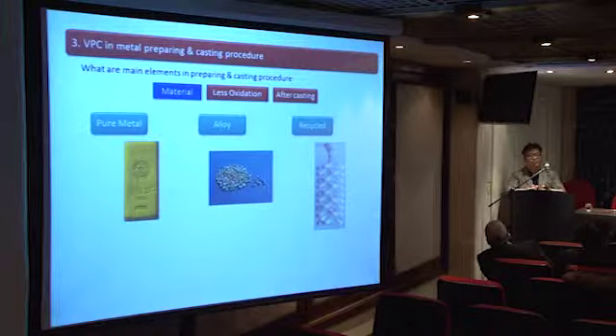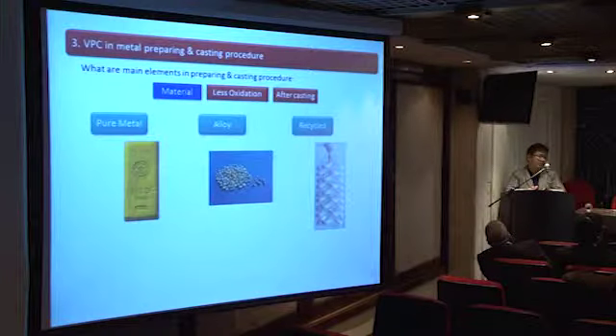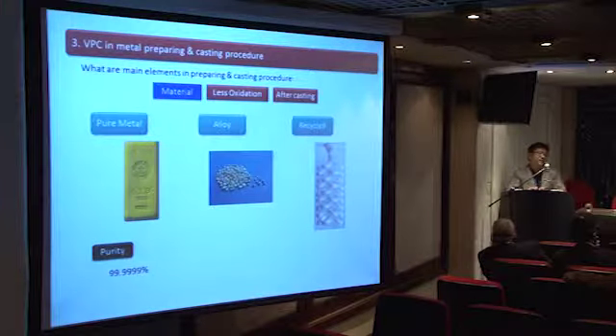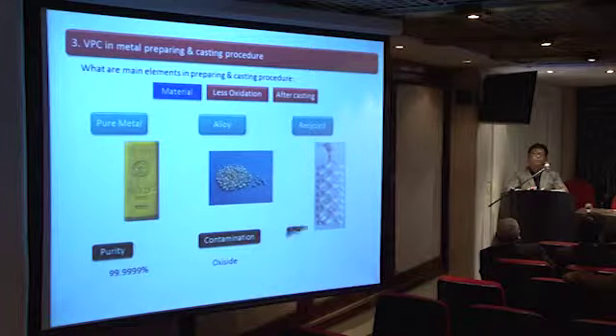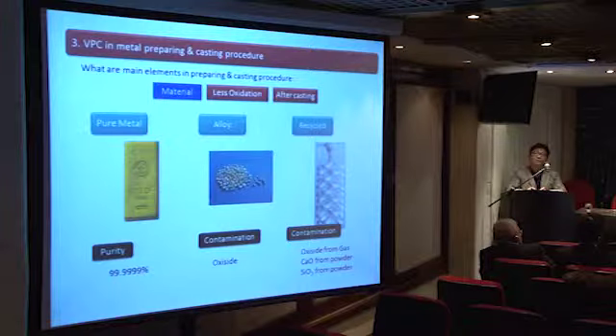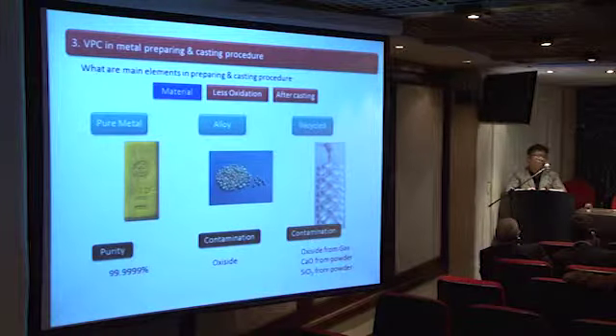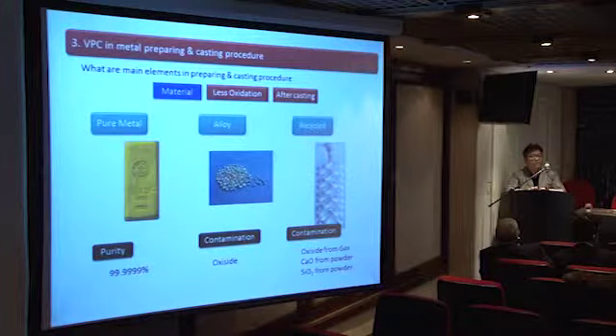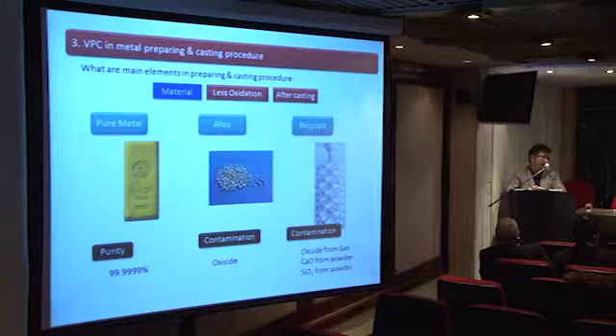To have all these in a good shape combination, you'll basically reduce the oxidation of your metal, which is coming from a lot of hard spots and gas porosities, which affect a lot your gold loss as well as your time of polishing. If you have an alloy or a recycled metal, a calcium oxide or oxidated metal, which is either from the powder or basically during the melting process, even if you're mixing with the pure metal, please consider that the metal has been oxidated.